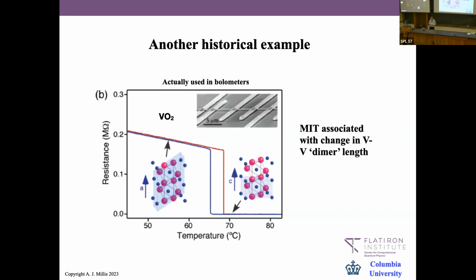Again, in this thing, it's kind of hard to see from these pictures, but there's an obvious change of electronic state and it's associated with a change in crystal structure. The red things here are the vanadium atoms. And although it's hard to see from this, basically the vanadiums come in pairs, and the length of the vanadium-vanadium dimer gets a lot shorter in the insulating phase.